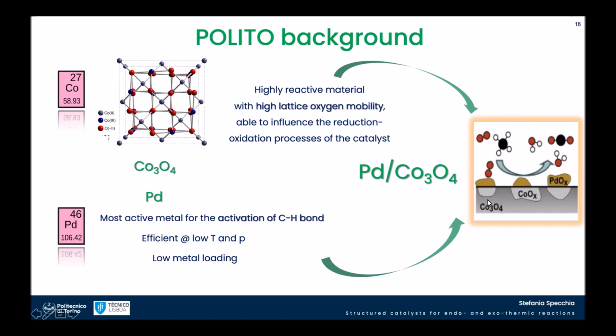And so we were using this ability of the spinel to keep palladium on the surface of the support as palladium oxide to promote methane combustion. And also palladium is very active. It is among the most active, much more active compared to platinum in promoting methane combustion. So we worked a lot in optimizing this palladium over cobalt spinel oxide.